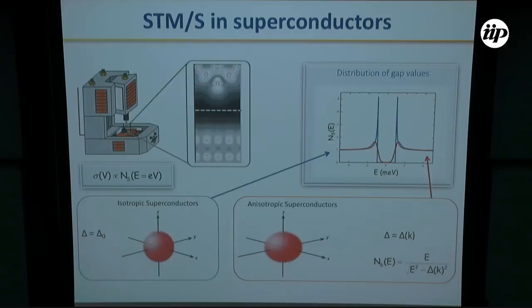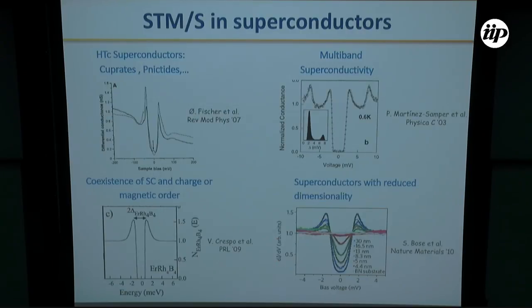This is not important in the case of isotropic superconductors, where we have a constant value of the superconducting gap over the Fermi surface, but it's indeed very important in anisotropic superconductors, where we may have a distribution of gap over the Fermi surface. So just by looking at the difference in the shape of the tunneling conductance, we can get information about the distribution of gap in the Fermi surface.